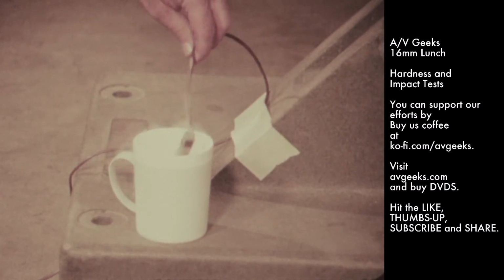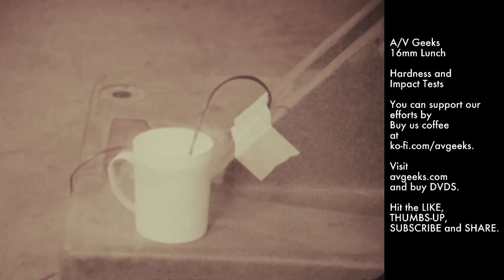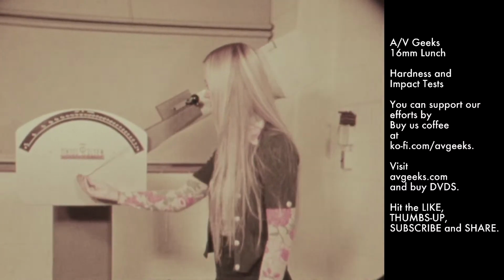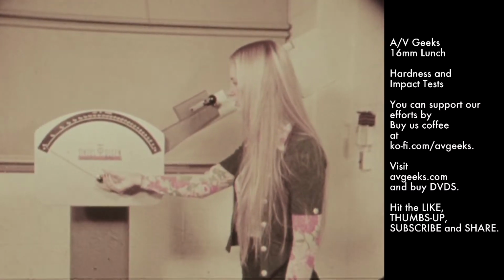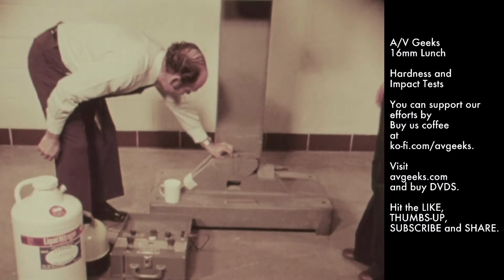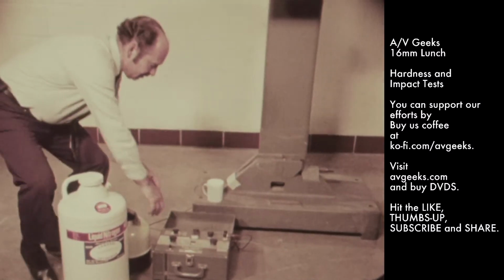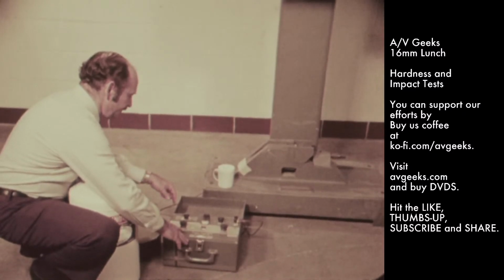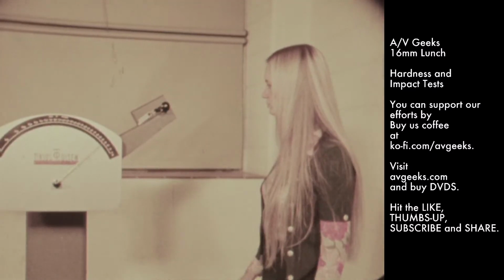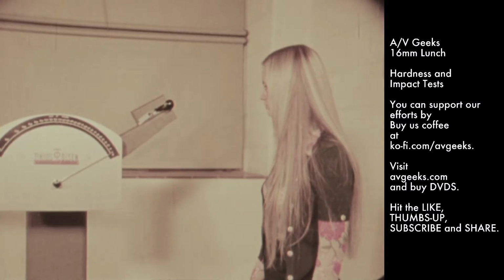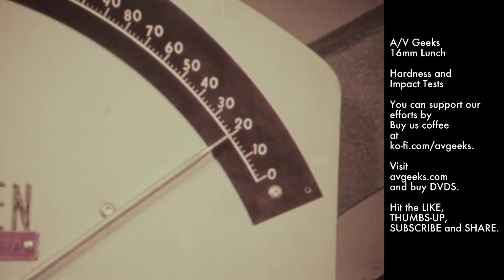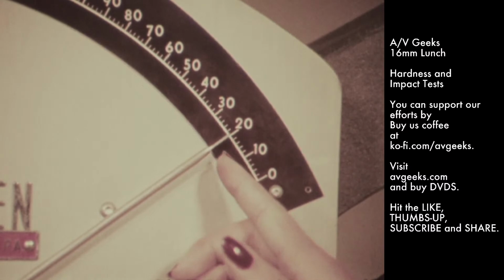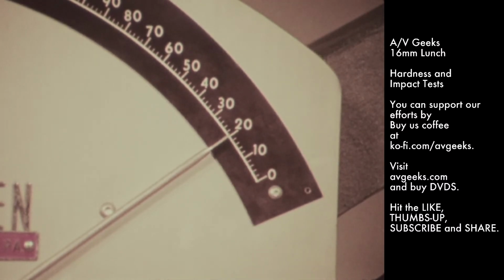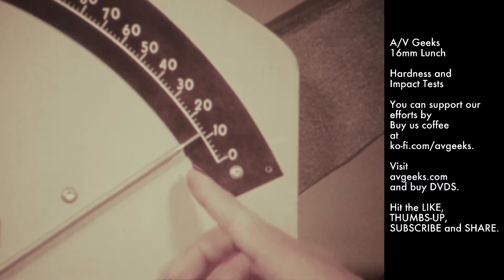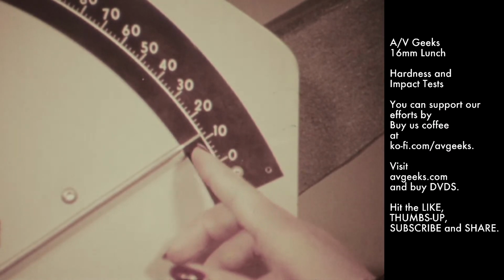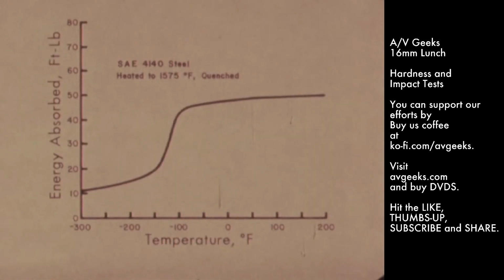A thermocouple is attached to the specimen in order to measure its temperature. After a liquid nitrogen immersion, the specimen is inserted into the impact testing machine, and its temperature is allowed to rise. When the temperature reaches a specified level, minus 170 degrees Fahrenheit in this case, the pendulum is released and the energy absorbed, 20 foot-pounds, is recorded. At minus 250 degrees Fahrenheit, the energy absorbed is still lower, 12 foot-pounds.